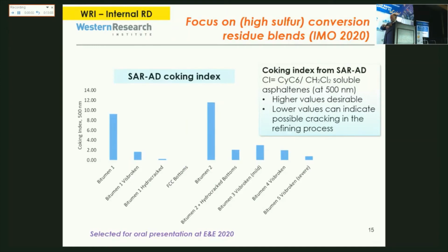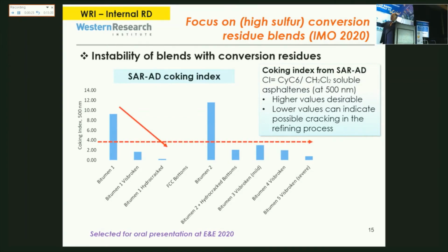Now, if we discuss a little bit about the conversion residues coming from IMO 2020, they are very unstable from a chemical standpoint. And we did some on purpose at the lab. And what we find out is that if we compare, for example, a base asphalt, so those are two base asphalts, and then we break them and submit them to a thermal process, then we make them more unstable. And this is looking at the coking index, which was developed for crude oils, and lower values indicate possible cracking in the refining process. So when we do this, things happen, and those are not chemically stable in terms of oxidation.